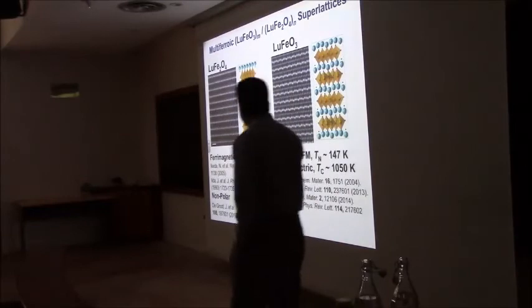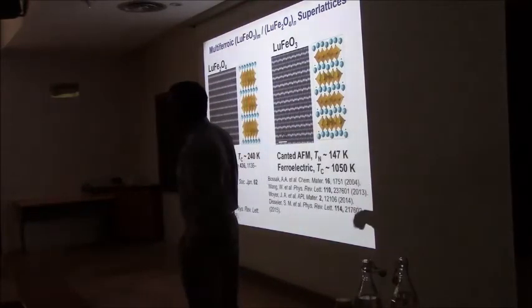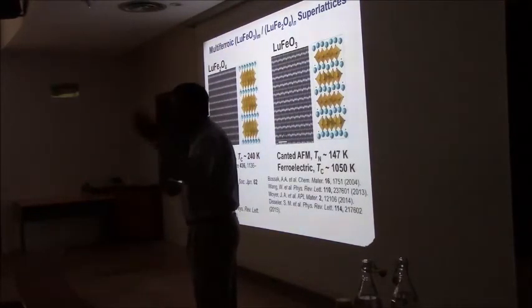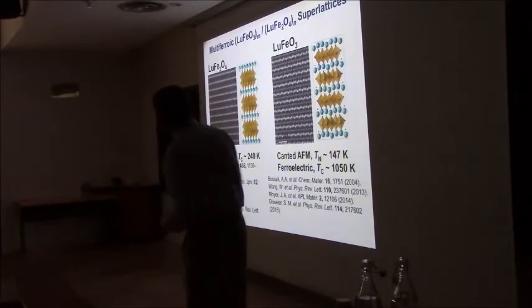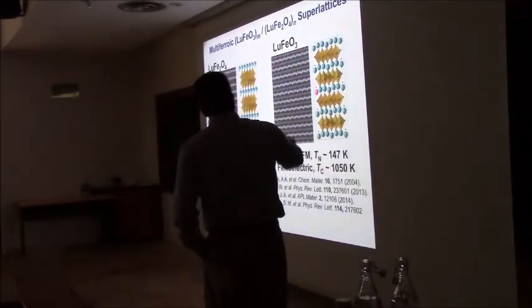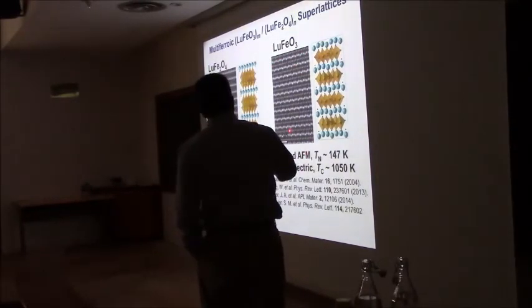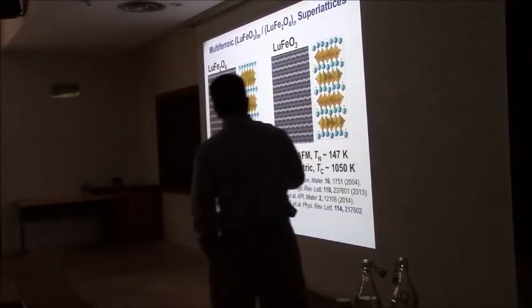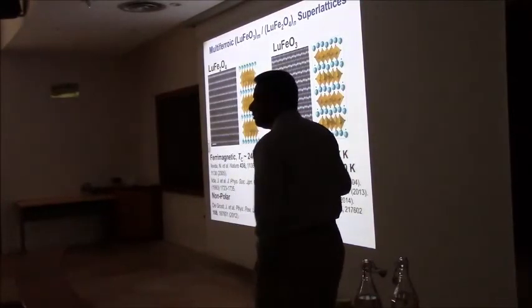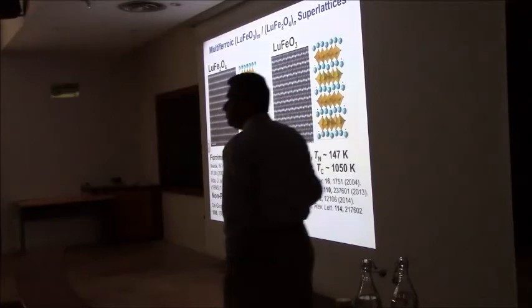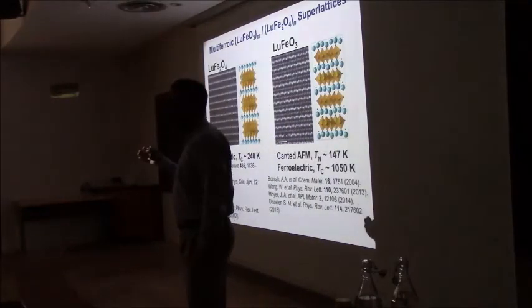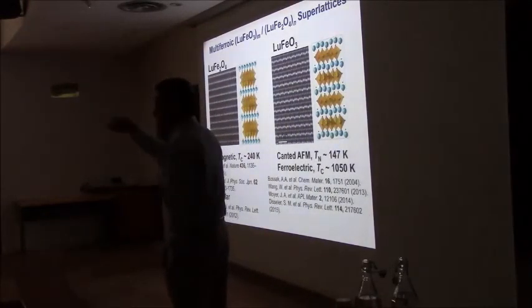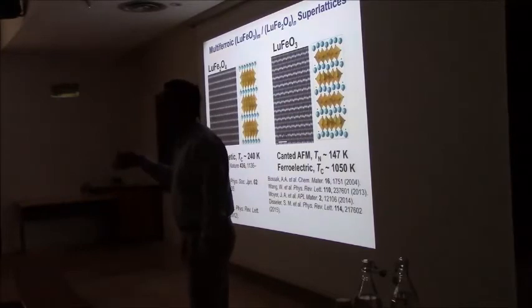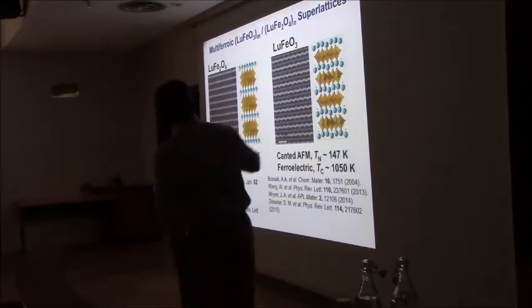It is definitely magnetic with a Néel temperature, or ordering temperature, of about 240 Kelvin. The 113 compound, lutetium iron oxide, on the other hand, is a canted antiferromagnet with a Néel temperature of about 140 Kelvin. It is ferroelectric at a very high ordering temperature. Felipe was talking about improper ferroelectrics, right? This is a good example of that.